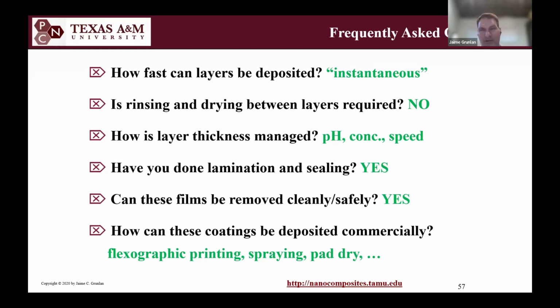I have a number of things I can play with, like pH, concentration, and speed, to change layer thickness if I want to. You can laminate and seal coated PET, for example. We've done it. And you could recycle these if you took it to very high pH: you could strip the coating off of a surface. And then flexographic printing, spraying. If you're talking about textiles, typical old-fashioned pad dry processing can be used to deposit multiple layers or even just the one or two-step polyelectrolyte complex treatments that I showed you.